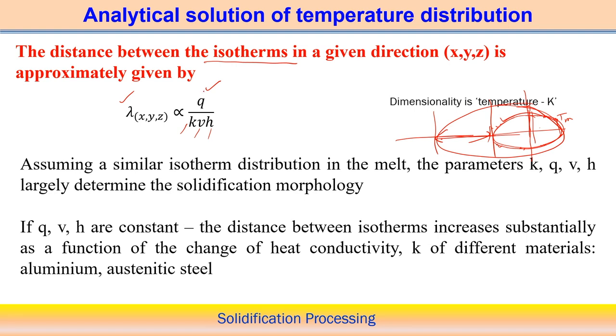Now, if we check the dimensionality of this expression, its actual dimensionality is temperature, and in terms of SI we usually put it in Kelvin. Now, if we assume a similar isotherm distribution in the melt, in this parameter you can see the variable parameters are the thermal conductivity, the heat applied to the plate, the welding velocity, and the thickness of the plate. All this matters to decide the isotherm. If we assume Q, V, that means the total heat applied, the welding velocity, and the thickness of the plate are constant, but the materials are different such that their thermal conductivity is different, then we can get this gap to be different.